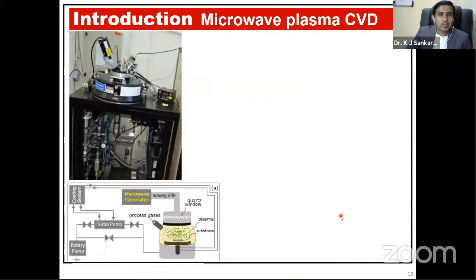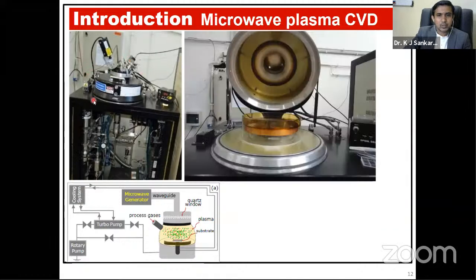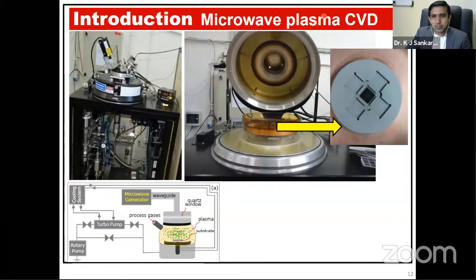Then this is the microwave plasma CVD. It is a very big system, around 7 feet, and this is the schematic diagram of this microwave plasma CVD system. This is the chamber where we need to place our silicon substrate. Once you open this chamber, you can see the inside part, and we keep the seeded silicon substrate on a substrate holder. This substrate holder is placed here, then we close the chamber and start pumping to create vacuum. The vacuum should be at the level of 10⁻⁶, so that there won't be any contamination during the diamond film growth. If you need high quality diamond films, it should be a high vacuum, better than 10⁻⁶, so that we achieve high quality diamond films.